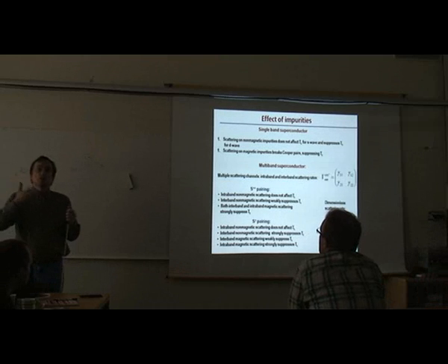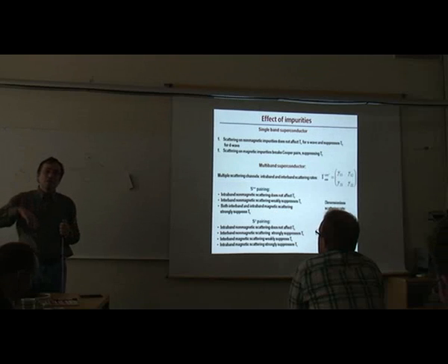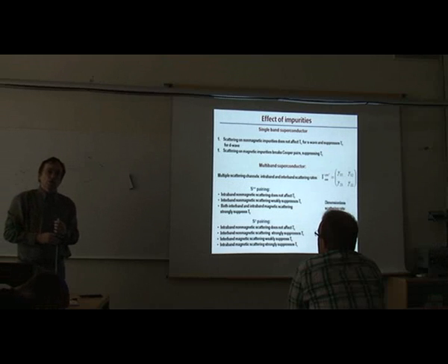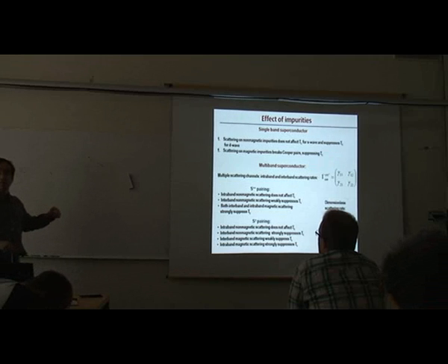But it seems that you need to fine-tune some kind of disorder potential to even try to achieve this. Well, in the model it's just a parameter, because if you take, let's say, zinc, people can calculate what part of the scattering amplitude produces intraband scattering and what part produces interband scattering. Then it becomes sensitive to the symmetry of the wave functions and all that. But usually a single impurity produces both intraband and interband. Yeah, exactly. So the intraband component doesn't suppress Tc, the interband component does.